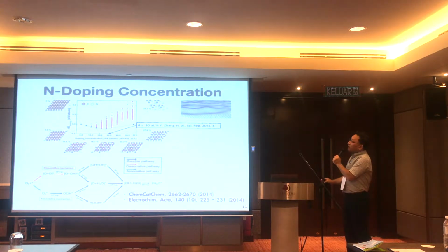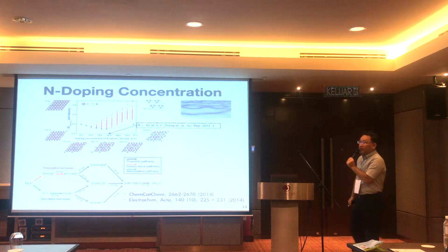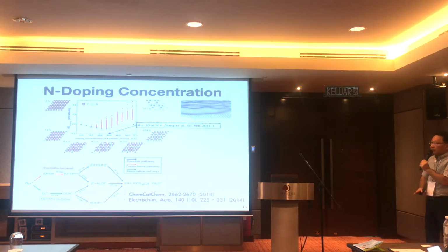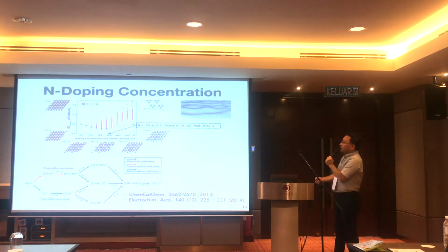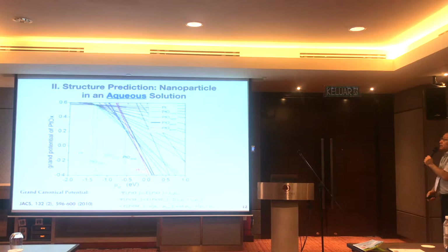How about graphene? Everybody is talking about graphene nowadays. Graphene by itself is not that good, but there is some behavior when adopting heterogeneous atoms on the graphene. For example, many people are working on graphene. This is a single layer of carbon, and can you dope nitrogen on the graphene? Of course you can, but you cannot go more than 30%. This is the maximum doping concentration of nitrogen on the graphene. If somebody reports, oh, we synthesized more than 30% nitrogen on the graphene, no, it's fake. Because more than 30% doping gives you two-phase regions. It is not really graphene doped by nitrogen, but it is nitride, not graphene. Okay, so that's also a thing.